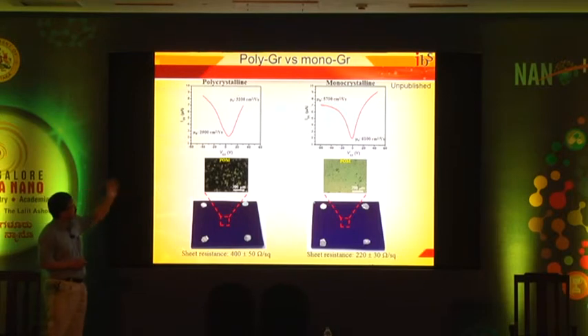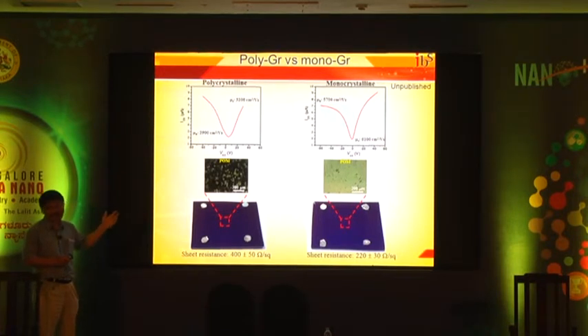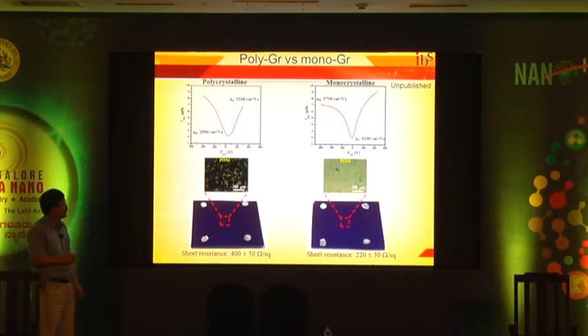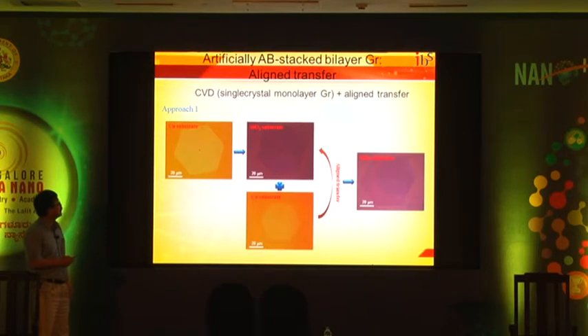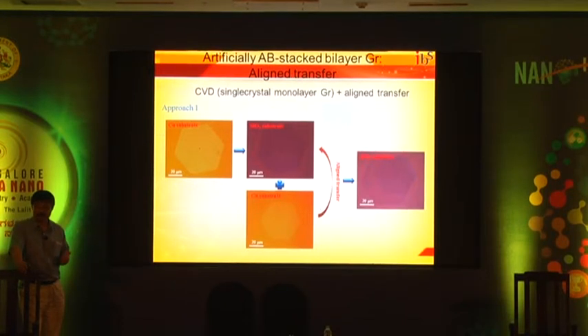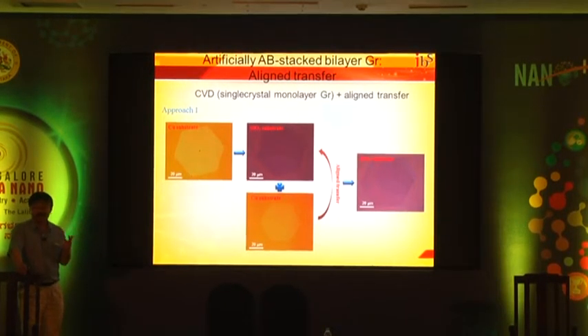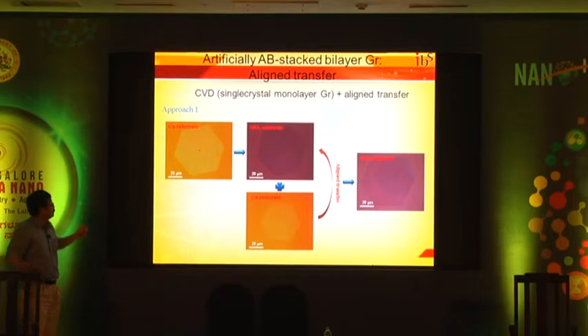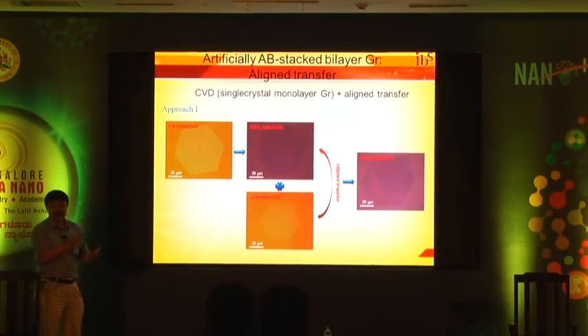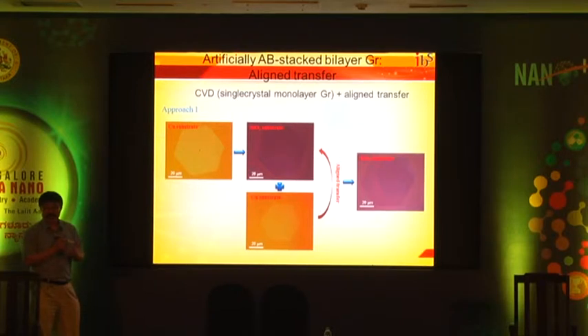Now, of course, the electrical conductivity and sheet resistance change as well. You can see the monocrystalline graphene improves the sheet resistance almost twice, as well as the mobility. Now, our next question is, can we really fabricate this bilayer graphene, which is AB stacking order, which is technically very important for switching device application? We need to have AB stacking in large area. Because we are able to get the monocrystalline large area graphene, we can actually overlap them together and get the AB stack bilayer.